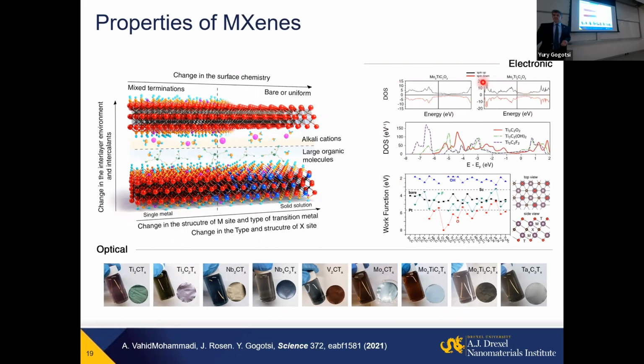And you can see from a couple of these density of states pictures at the top here. You change different elements and you see different colors. And you have a complementary plasmonic color. For example, titanium 2C will be red-purple in solution and green in reflection. And this is a classical case of gold nanoparticles, with the only difference that you have very common elements, titanium and carbon, no gold. And this is the same color that the Lycurgus cup, from the 4th century, this classic example of nanotechnology, gives you, which is green in reflection and red in transmission because it contains gold and silver nanoparticles. And it's often cited in nanotechnology books and popular literature as a first example of human-made nano systems.